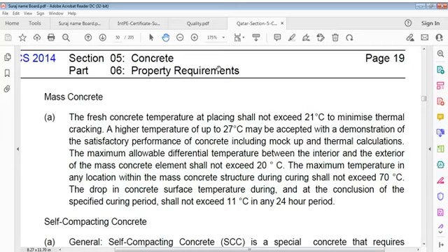Maximum temperature in whatever location within mass concrete or massive concrete structure during curing shall not exceed 70 degrees Celsius. So the difference of temperature is 20 degrees between internal and external of massive block, and maximum temperature in whatever location within mass concrete structure during curing shall not exceed 70 degrees Celsius. Drop in concrete surface temperature during and at conclusion of the specified curing period shall not exceed 11 degrees in any 24 hours period.